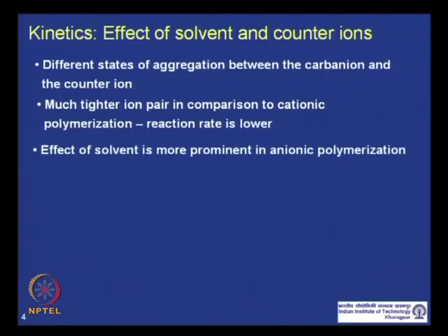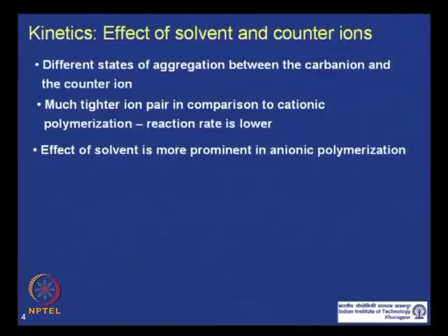Because in anionic polymerization in a non-polar medium they are tight, consider the effect of solvent polarity. If you increase the polarity for both cationic and anionic, the effect in anionic polymerization is much higher, because to begin with they are much tighter, and if you increase the polarity they can become free. So, the reactivity goes up.